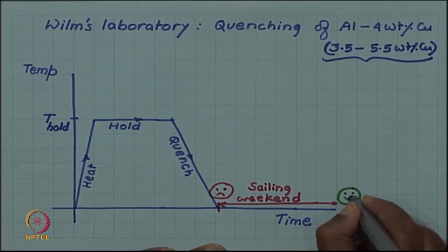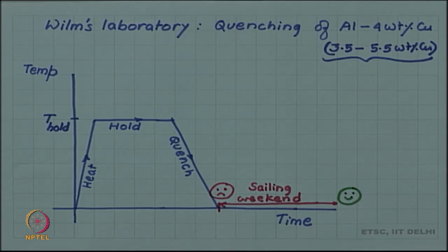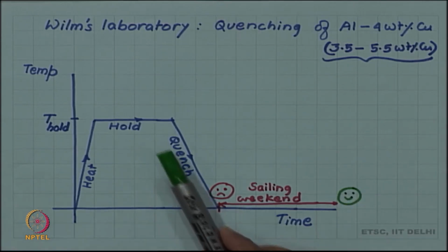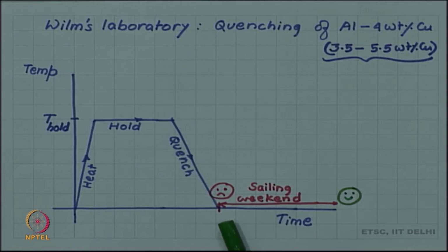So, finally, his research was successful. He found a way of increasing the hardness. Hardness does not increase simply on quenching, but quenching and waiting. That is, as the time passes, hardness seems to increase. He did not have an explanation, but experimentally he could prove that hardness is increasing as a function of time.